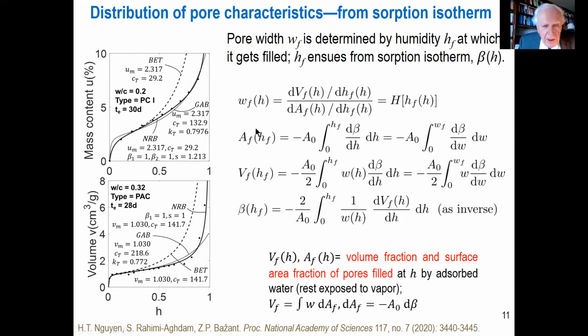Now, from this, we can calculate the volume of content in the pores. And now what is a convenient parameter is the volume fraction of surface of pores. Here, what is convenient is a pore width determined by the pore humidity HF, at which the pore gets filled. And for knowing that, everything else follows.